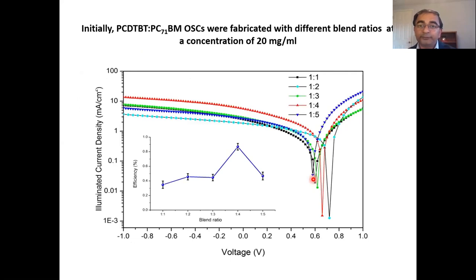So you can see from here what we have done. We have made solar cells with different blend ratios, 1:1, 2, 3, 4, and 5, and this is the efficiency plot. You can see from here that at the 1:4 blend ratio we got the highest efficiency compared to other blend ratios, and you know the reason, because absorption is more at 1:4 and your roughness is more at 1:4. So when you study thin films and you study solar cells, you can correlate the things with that. Now we have used 20 mg per ml concentration.